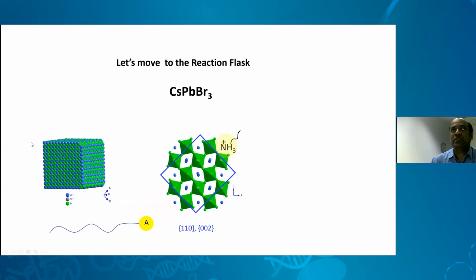that deal with the cubes, which have been analyzed here. It was found that the culprit here is the ammonium ion. This ammonium ion is exclusively stabilizing this type of facets, putting it in one of the positions of the blue balls, or the cesium remains. So that's how they are getting the cube.